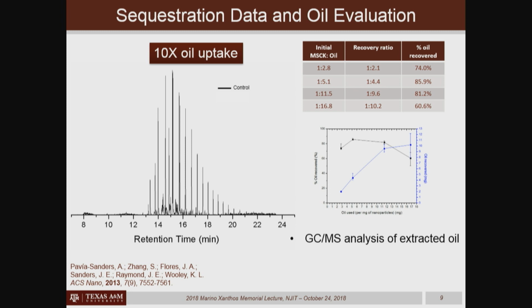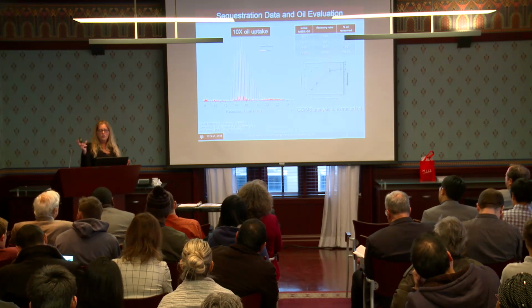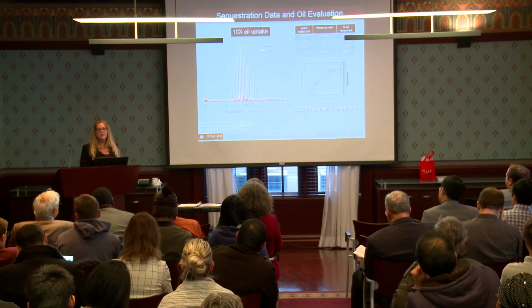And that's seen by the GC mass spec trace here. And then after the crude oil had been captured by the particles, what we find is that the GC mass spec trace basically overlays. So even though these particles are simple, they're comprised of polystyrene, polyacrylic acid, cross-linked through these triethylene glycol diamino cross-linkers, they can capture this complex mixture of hydrocarbons.